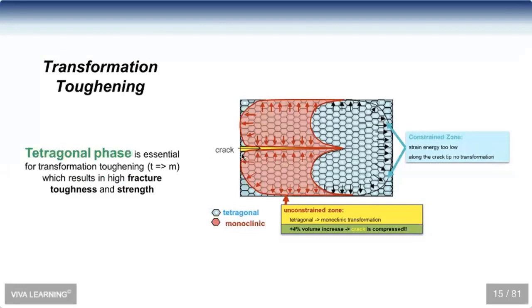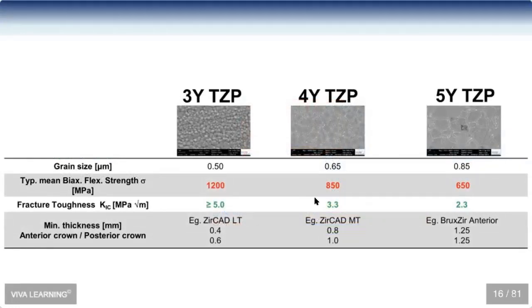And again, that transformational toughening is what makes us able to hit a zirconia crown with a sledgehammer and drive it into a piece of wood. When a crack starts, the crystals inside, because of the energy of the crack, they change from tetragonal back to the monoclinic, and they close that crack and keep it from happening. Now, it will only do this magic, well, it's not a magic trick, but it'll only do this transformational toughening a couple of times. So if you hit it with a sledgehammer 3 or 4 times, it eventually breaks. But we've never had a material in dentistry with the ability to actively resist these kind of cracks and have that type of fracture toughness numbers. And you can see that's why we get crazy numbers.